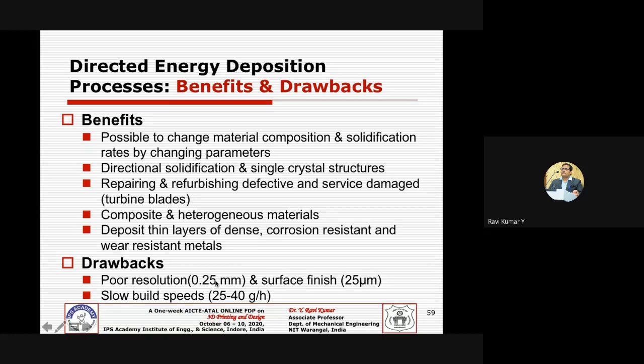As built, I am talking about, post-processing you can improve, and the as-built surface finish is around 25 microns. The slow build speeds may be 25 to 40 grams per hour, typically, so that's not a great speed. But this is the existing scenario I'm talking about. A lot of developments are happening, as we discussed previously, as far as speed is concerned. And still the accuracy is the major challenge here, and surface finish too.